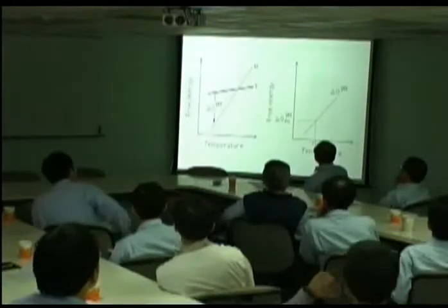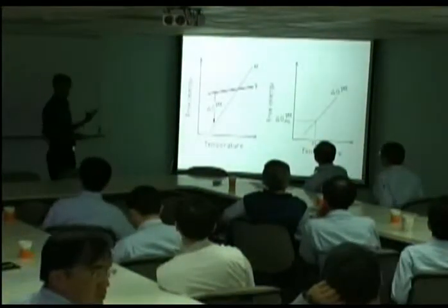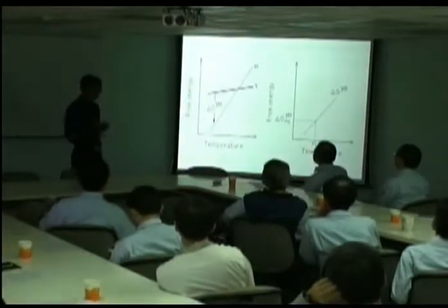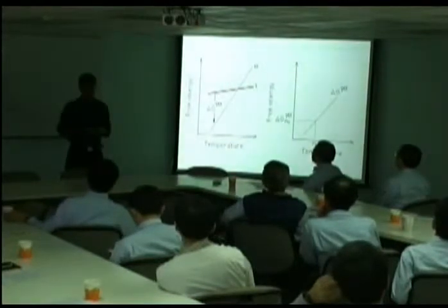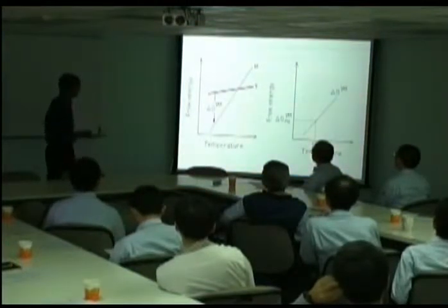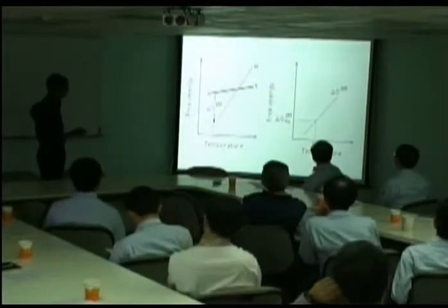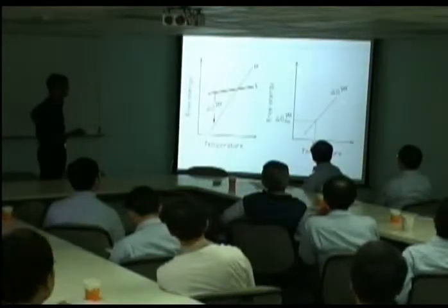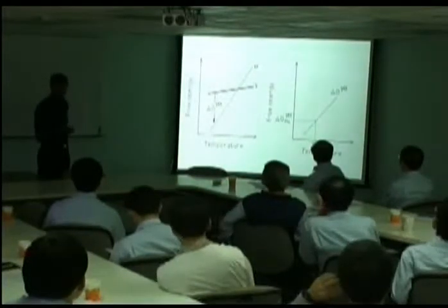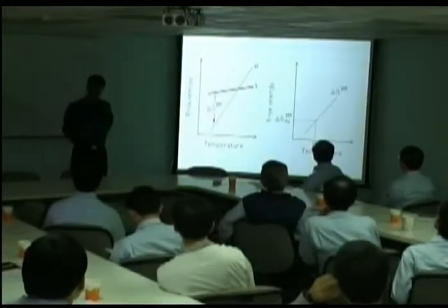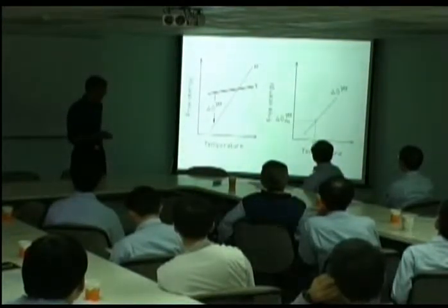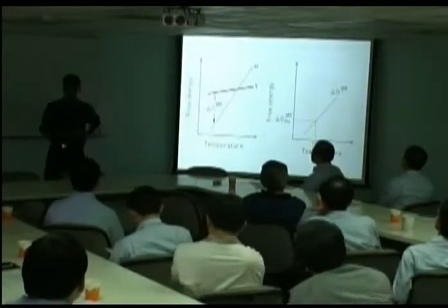Right, and I need to also show you how we do a calculation of the MS temperature, the martensite temperature. Well, that is very, very easy. Everything is diffusionless. Nucleation is diffusionless, growth is diffusionless. So basically, when the free energy change for diffusionless transformation reaches a critical value, we get martensite. So it's very easy to calculate the martensite start temperature in any steel. All we have to find is the temperature at which the free energy reaches a critical value.